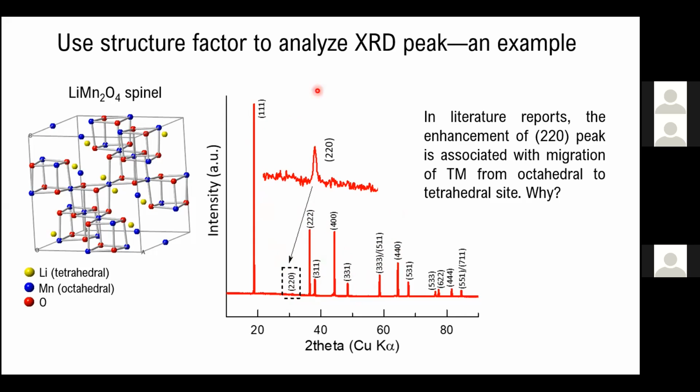But in fact, there should be more systematic absences, right? Because actually we have the d-symmetry. And if you remember, the glide plane is also a kind of translational symmetry. So we have d here, and that will eat up some additional peaks, right? So we should expect fewer peaks than for simply the F cubic system.